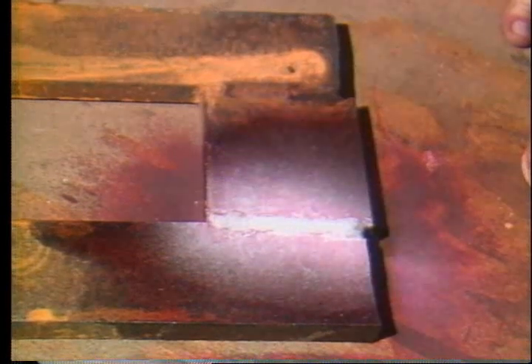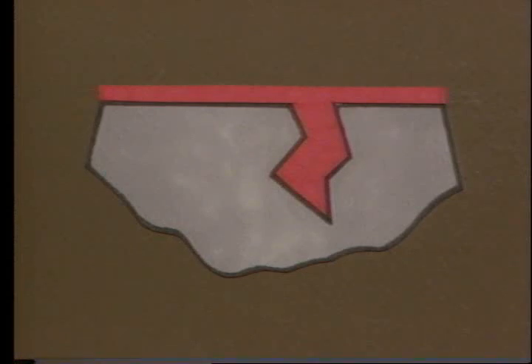About ten minutes after applying the penetrant, all of it is removed — this is the most critical step. The best way is by using cleaning solvent and chem wipes; spray the solvent directly into the rags as it evaporates quickly. The area is clean enough when a fresh rag remains clean after being run across the surface. If a defect exists, the penetrant will be trapped in it even after cleaning. The developer — a fine white powder — is then sprayed on, drawing the remaining penetrant out of any defect by capillary action. A dark color, in this case red, appears along any defect. Always have a qualified person check any defect you find. LP is most suited for smooth machine surfaces like ram rods.